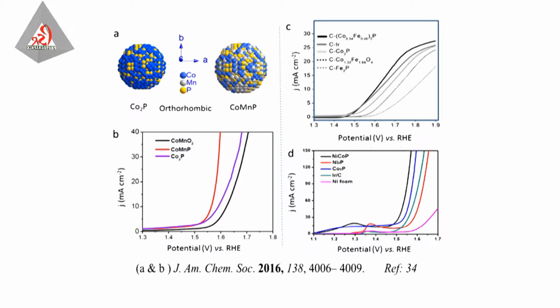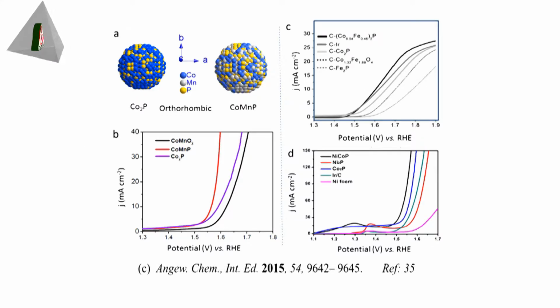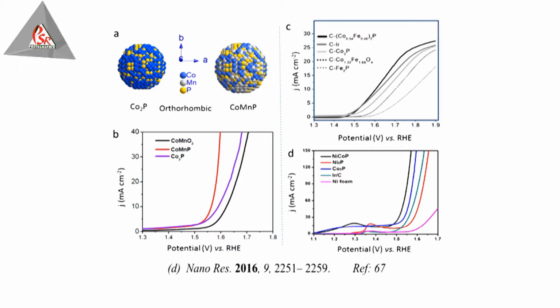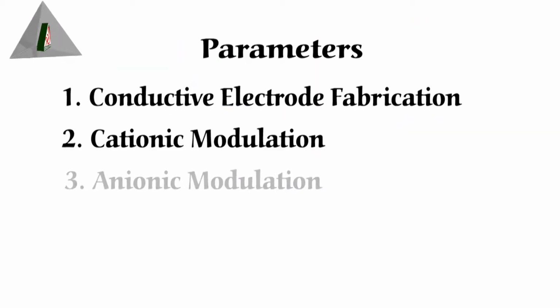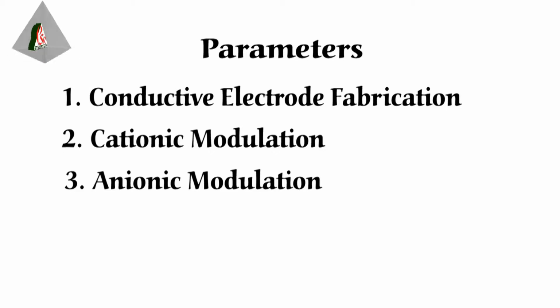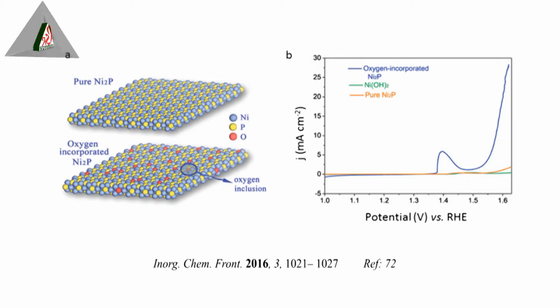In several cases, manganese and iron incorporation into the lattice of cobalt phosphide boosted the efficiency of the material. Anionic modulation: not only the cationic modulation, anionic modulation also plays an important role in the activity. For example, incorporation of oxygen in nickel phosphide and cobalt phosphide enhances the activity drastically.